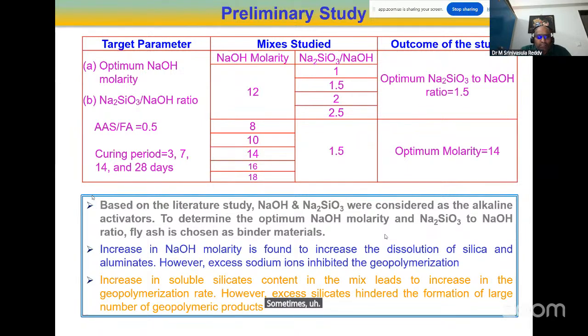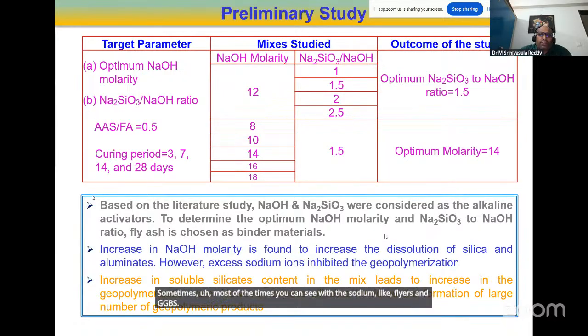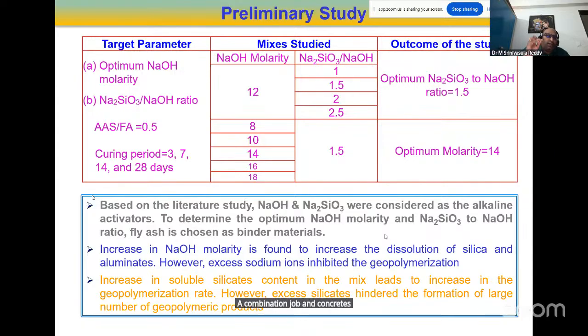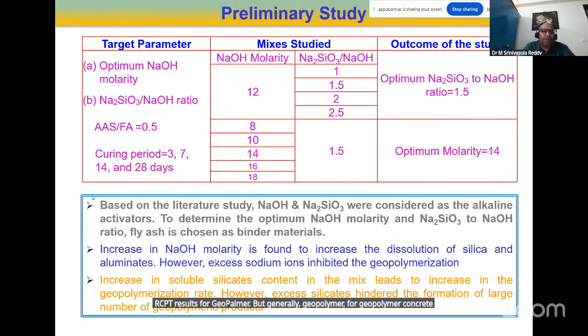Most of the times you can see with fly ash and GGBS combination geopolymer concretes, you see white layer formation because of the excess amount of sodium present in it. And also it will affect your RCPT results. I observed many people reporting RCPT results for geopolymer. But generally, for geopolymer concrete, this RCPT will not work.